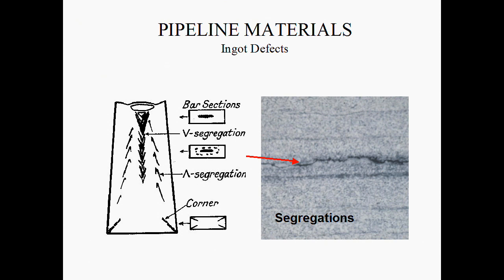and metallurgists discovered over 100 years ago that if you took a cut section of surface and polished it to a mirror finish with various silicon carbide papers and diamond grits, and then you applied a very dilute acid, sometimes an acid in alcohol, you could actually reveal the structure of the material within the ingot. And here is an example of such a micrograph, and what you can see is these little cracks due to the segregation in the system. And you get cracks from the corners, you get these chevron cracks, and you get these V cracks all the way through the system. And they're basically driven by segregation and the cooling patterns.